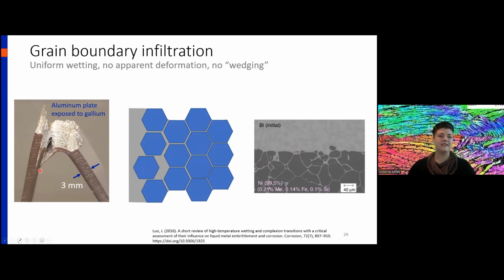So looking at this aluminum specimen that was exposed to gallium, you can see the plate-like morphology of the grains because it is an as-rolled plate, and you can see it literally peeling apart at the layers between the grains. And then in this bismuth nickel specimen, you can see a uniform film of liquid sitting along the grain boundaries.